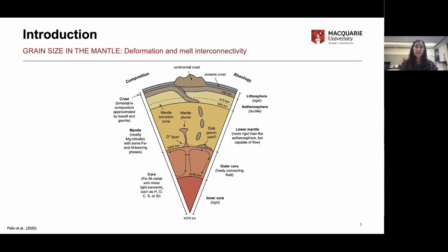And the fact is, the Earth isn't composed of just one mineral, even though many experimental petrologists would lead you to believe it is. We have bimodal or trimodal compositions, and this makes understanding what the grain size is hugely complicated. We understand that for the upper 200 to 300 kilometers of the Earth, we're deforming in a dislocation creep regime, which hints at there being large grain sizes.